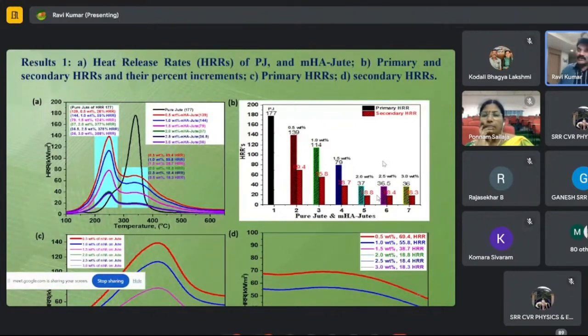Also, you can see the primary HRR and secondary HRR, which means we studied the heat release rates two times, the first time and the second time. This is the primary heat release rate and this is the secondary heat release rate. We studied this only by instrument; we cannot study it directly by naked eye. You can magnify this HRR, the primary and secondary heat release rate, and easily observe it. Image B shows very clearly against pure jute that we achieved a much better heat release rate compared to the pure jute with 3 weight% of MHA on the jute.